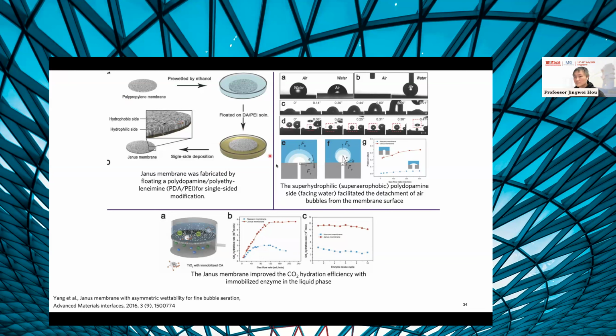We later performed quite systematic calculations on all the surface energy, etc. But long story short, once we use the Janus membrane, we can reduce the bubble size of the aeration by a significant amount. And that means smaller bubbles, much higher mass transfer efficiency. So if you compare with the gas dissolution speed, our Janus membrane is much higher in terms of the mass transfer efficiency in this case.